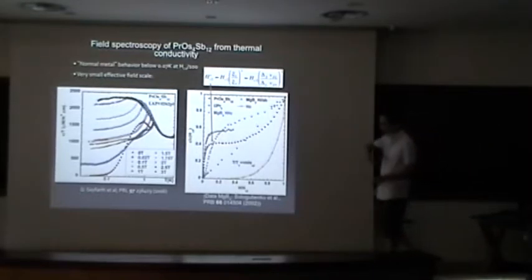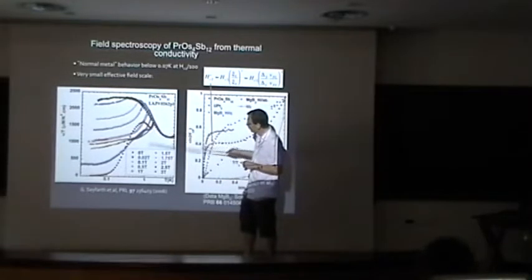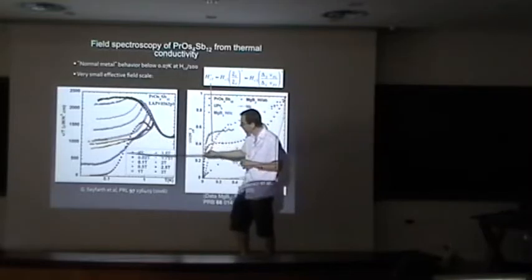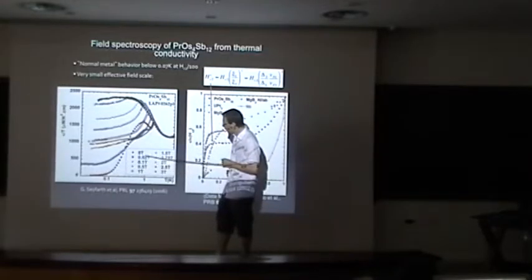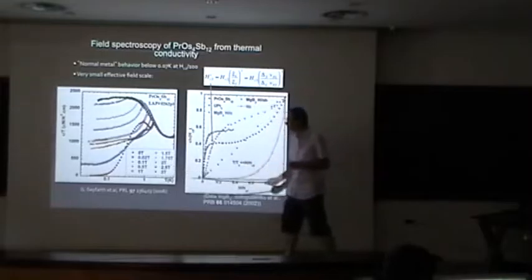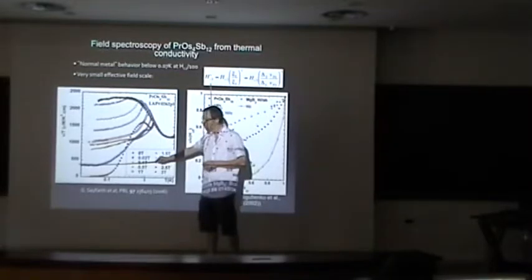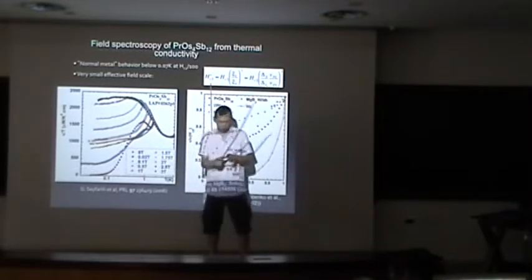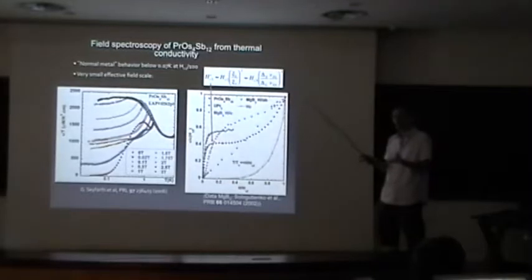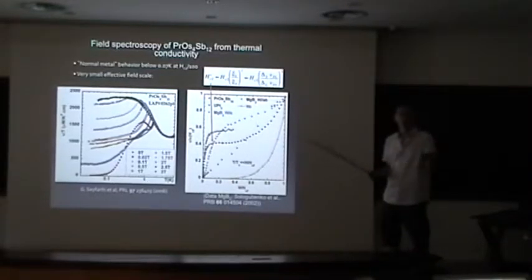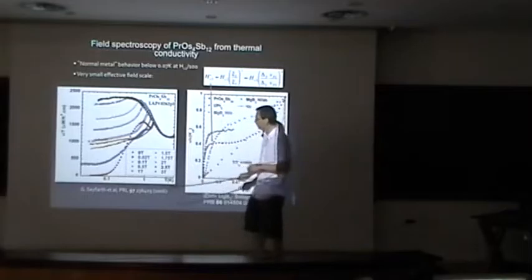And this is also to show you it's not only this value at low temperature which tells you that you have multigap superconductivity. If you look at the data now as a function of temperature at different fields, this is again the data at zero Tesla, which shows a very quick rise at low temperature. In a field of 20 millitesla, so the HC2 in this compound is around 2 Tesla, so it's a hundredth of HC2, you recover a constant behavior as you have in the normal state. This is really the picture I told you yesterday, that for the small gap band, when it's still superconducting, essentially vortices overlap, and you can consider that this band is basically normal. This is probably what happens in this compound, so you have a normal state conductivity due to this band with a small gap.